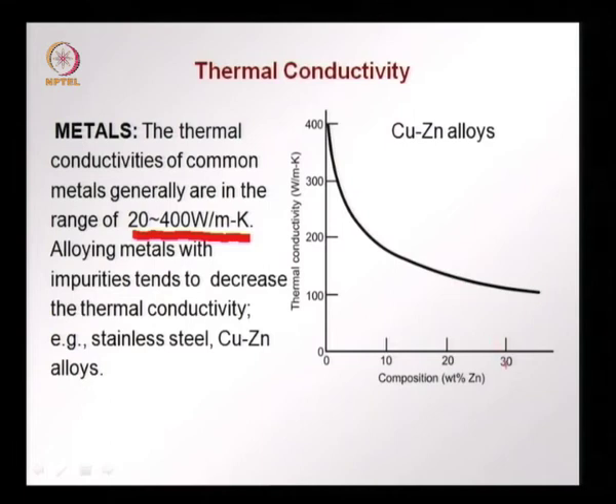So, we find that as more zinc is introduced into the copper, the thermal conductivity drops, that is the lattice has less possibility of transferring the heat as more impurities in the form of zinc are put in. Generally we find that alloying metals with impurities tends to decrease the thermal conductivity, as we see in this case in the copper zinc alloy and also in stainless steel.